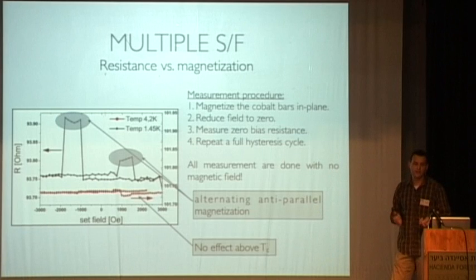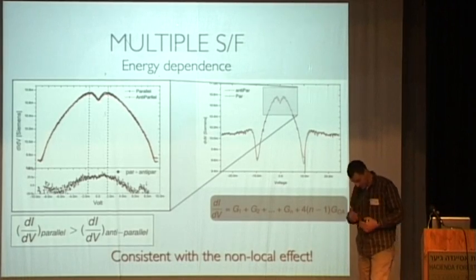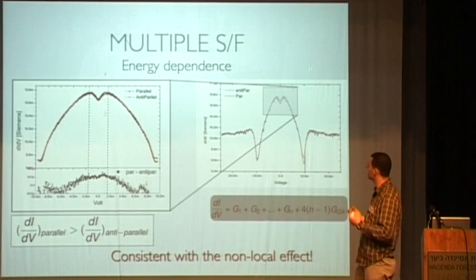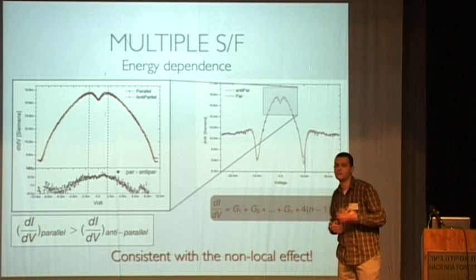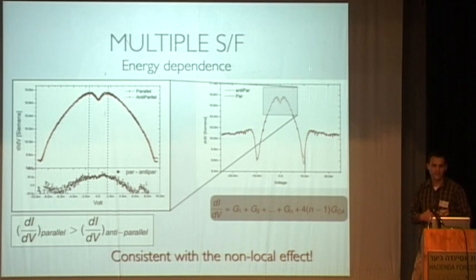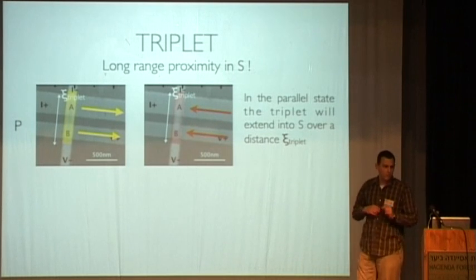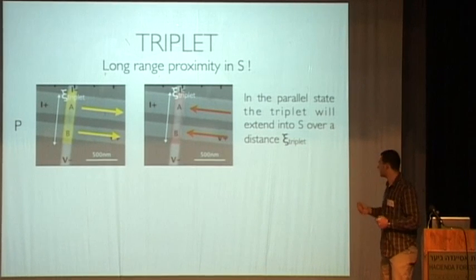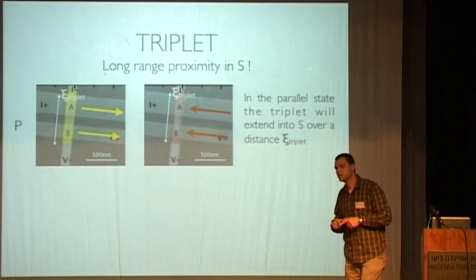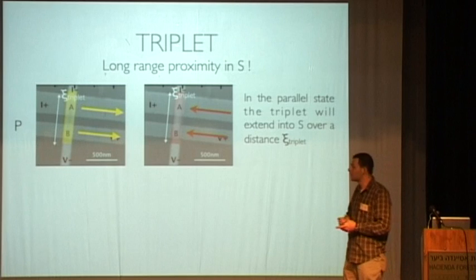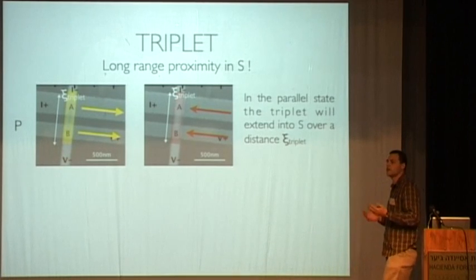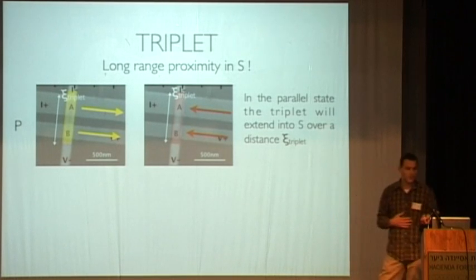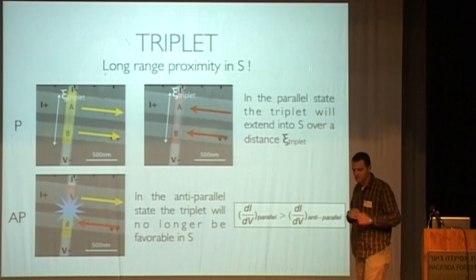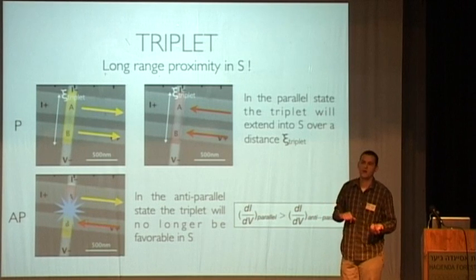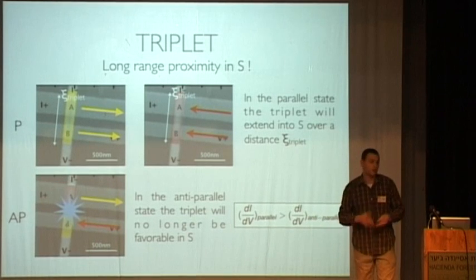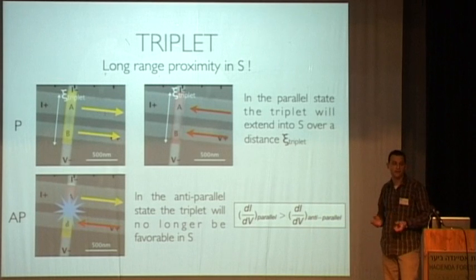And is it really due to Andreev reflections? The answer is yes. We measure the conductance or the resistance as a function of energy, and we see this effect only below the energy gap, at low enough energies. At high energies, this effect disappears, which basically means that this is due to the Andreev mechanism. Now, this is almost the final slide. What I showed you is actually a summary. I showed you that at a parallel configuration, a triplet order parameter is created, and it extends inside a superconductor what we call a long range. Basically, it's at least 100 or 200 nanometers, which is quite large in these systems. And this triplet mechanism is destroyed when you go into the anti-parallel configuration, because each triplet is polarized in the opposite direction. So the triplet components collide. You can think of it as a collision, and this mechanism is non-effective in the anti-parallel configuration.